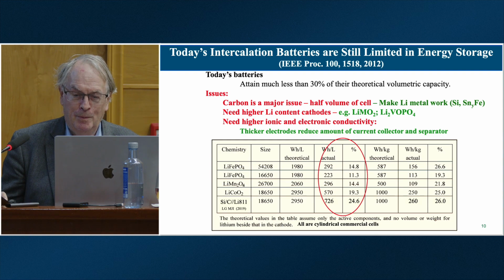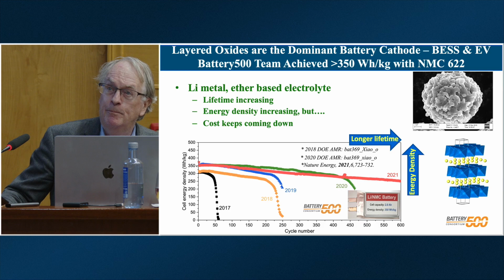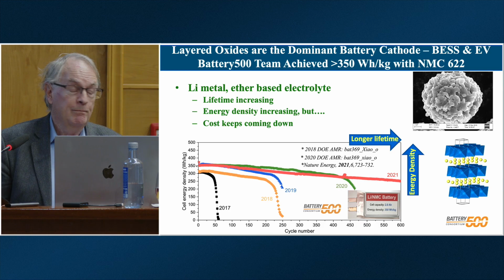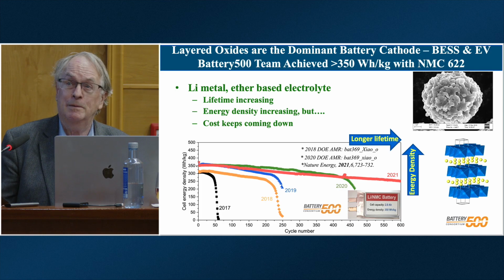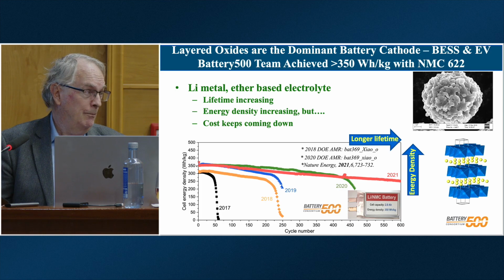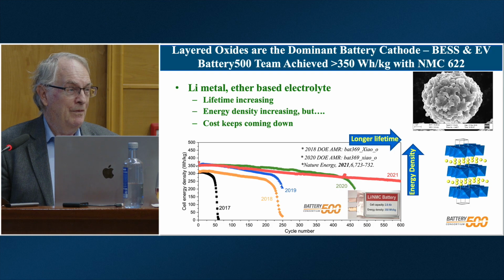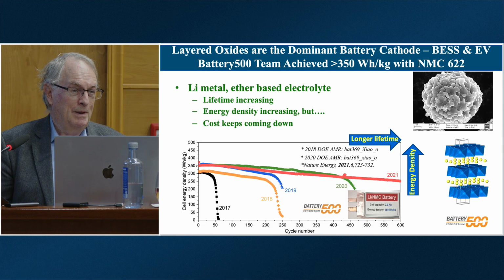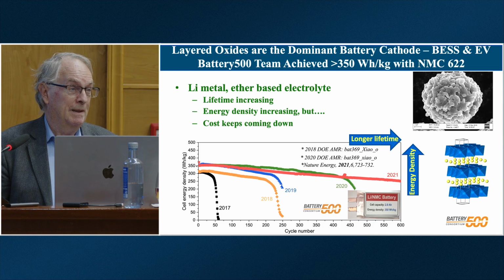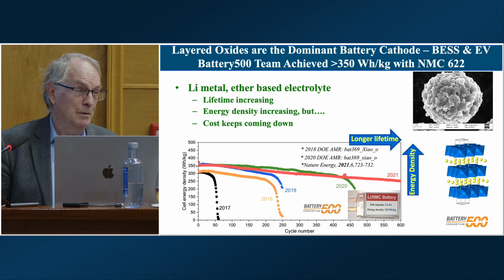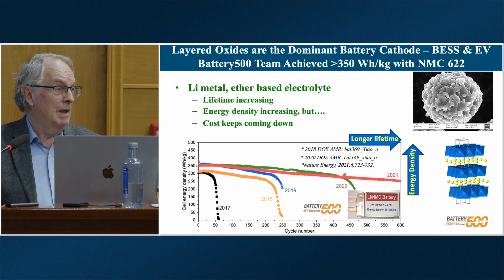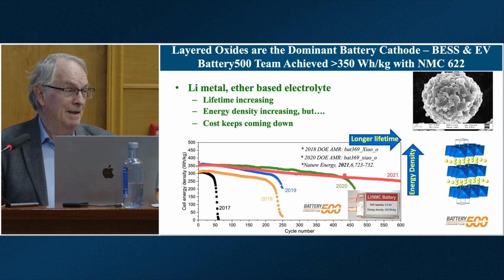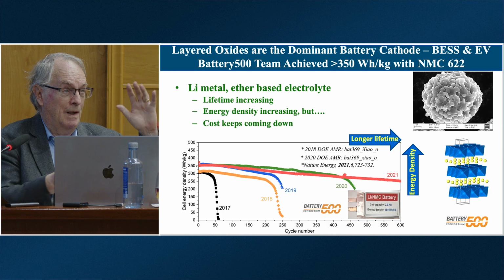Okay. So where are we on that project? We're 5 years into it. In this project, we're using lithium metal again. We're going back to where we started out. Mostly on this project, we're using ether-based electrolytes. This is where Exxon worked originally, and those of you who have done electroplating will know that the ether-based electrolytes plate out metals much better than the safe, stable carbonate electrolytes that are used with the graphite anode. We can't easily use ether-based electrolytes with graphite anode because they solvate the lithium ions and they go into the graphite, the solvent plus the lithium, so it swells the graphite enormously.